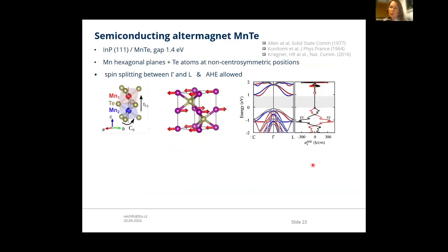Good. So let me move to the less controversial system, let's say, which is one of our beloved materials, manganese telluride. We have thin films and also bulk, which is a semiconducting material, and here the manganese atoms are surrounded by these tellurium cages, and with this kind of rotation and translation symmetry, it fulfills the criteria of altermagnetism. And indeed, already some time ago, calculations showed that the splitting is present outside of the high symmetry directions, and the anomalous Hall effect is allowed.